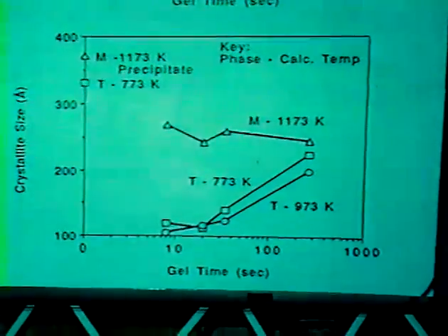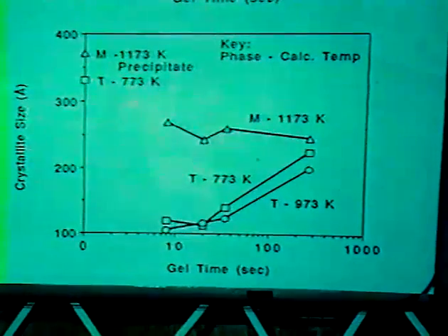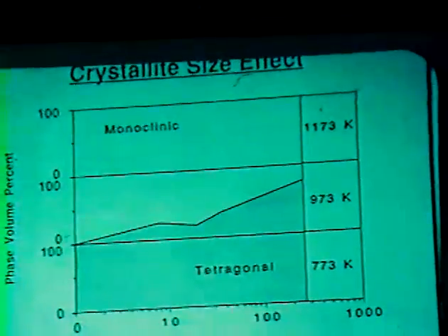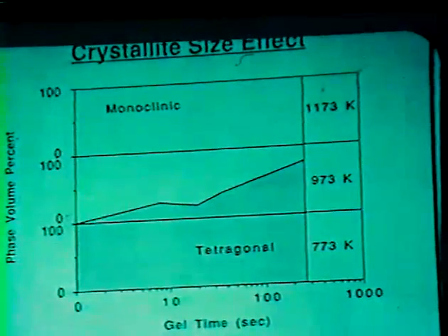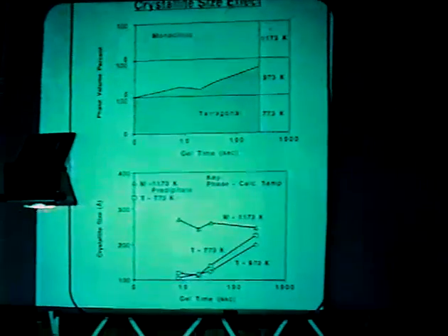One possibility is the crystallite size effect as proposed by Garvie and others, in that when you have very small particles, then the surface free energy term dominates, leading to the tetragonal form being the more stable form. We would like to present some new results suggesting that crystallite size effect by itself is inadequate in explaining this structural stabilization. There's a lot of information on this graph, so let me lead you through it.